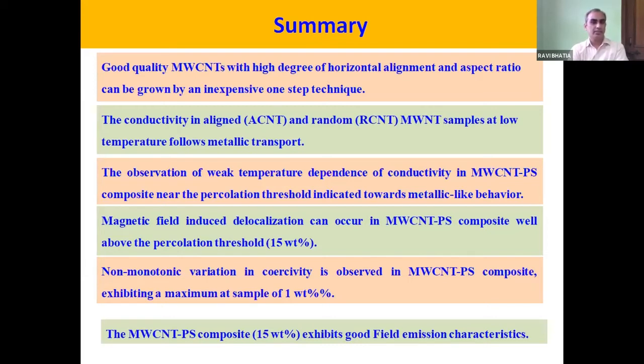And the next point talks about the magnetic field induced delocalization of carriers when you have a sufficiently large amount of CNTs incorporated in the composite, that is 15 weight percent. The magnetic response which was studied shows a non-monotonic variation of coercivity, and it shows the maximum at 1 weight percent. This particular work needs to be either verified or validated by some theoretical modeling, which we couldn't do so far. And the last is about the field emission properties at an intermediate level of filler loading. We got the highest current with the lowest threshold voltages.